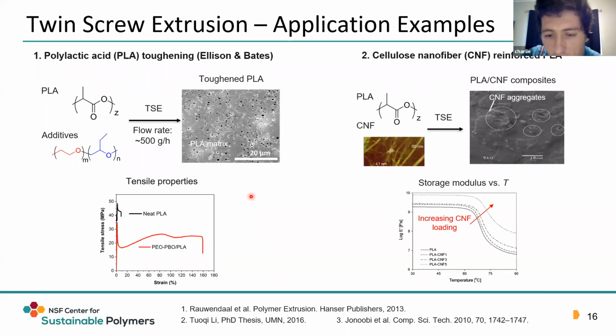Another example is PLA that has been fiber reinforced composite with the cellulose nanofiber. As you can see, as you increase the cellulose nanofiber loading, the modulus increases.